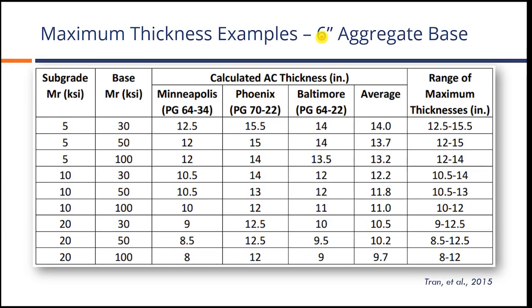Once we had the concepts worked out and the software developed to where we could use it to do some what-if type scenarios, we were able to do a study, and this particular one was led by one of our NCAT research professors, Dr. Nam Tran. He led this investigation. What we did is we looked at a variety of support conditions, different foundation conditions, from relatively soft to relatively stiff, and then varied the base stiffness, the aggregate base, from, again, relatively soft to stiff. Looked at a few different climate zones, from cold to desert to more moderate, like we have here in Alabama. And then we tried out different base thicknesses.